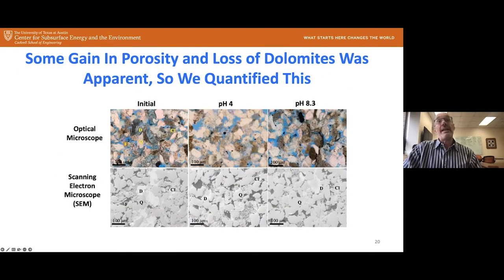The next thing was to look at the images. I already showed you these initial images on the far left. But then after the experiment was done, we took the very top or the surface of those cores that were in contact, and we created thin sections out of those. And we did it for the experiments that were done at pH 4 and then for the reservoir simulated brine. And just observationally, it looked like we got more open pore space in these images at the lower pH and less dolomite compared to the reservoir simulated case, and certainly compared to the initial case.